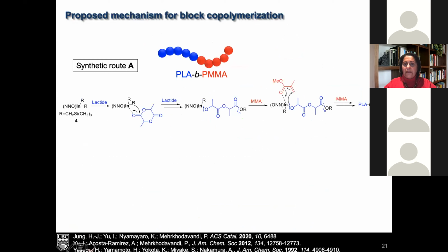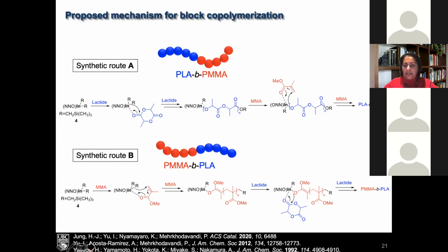And what's really exciting about it is that the formation of this material is completely unrelated to the order of addition. So we can either add the lactide first, and we know that that chain end is that alkyl group. It's a good enough initiator. We can form the alkoxide, and then the methyl methacrylate, once it's added, goes through a Michael addition reaction to give us the block copolymer, or we can go through that alkyl group, the indium TMS methylene group, which is a good enough initiator to actually start off the Michael addition reaction. Once you get the first one, everything else goes.